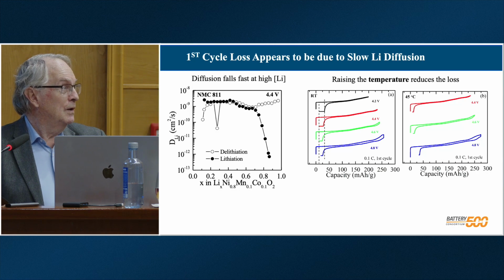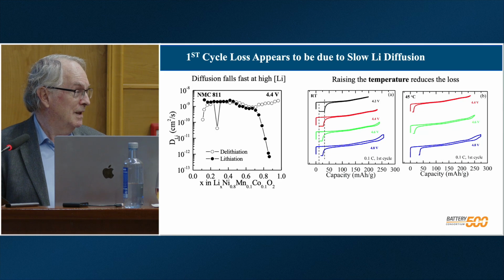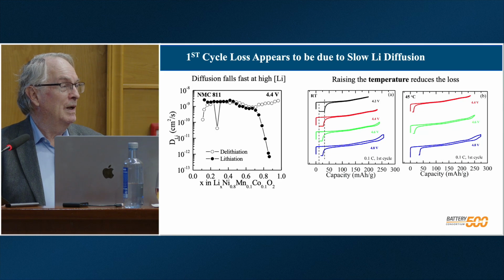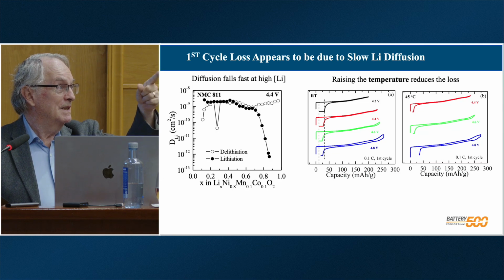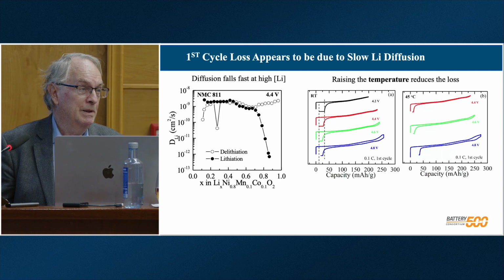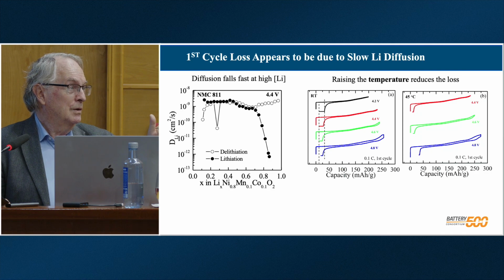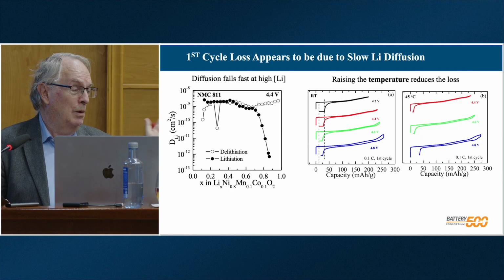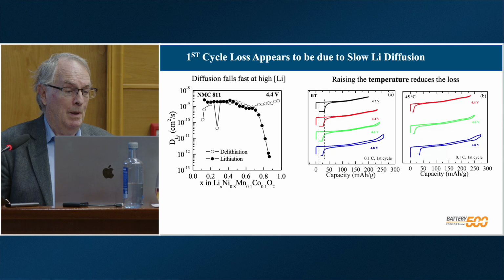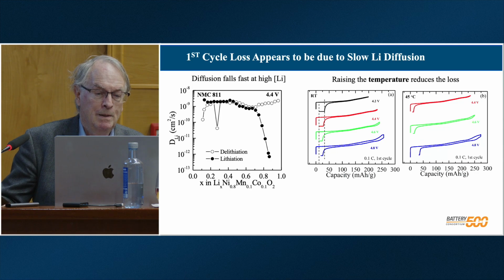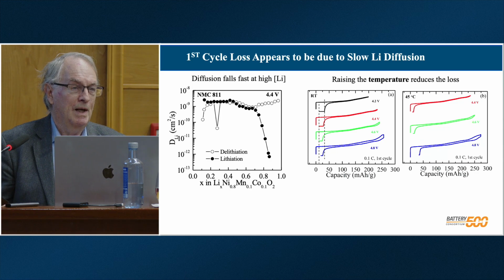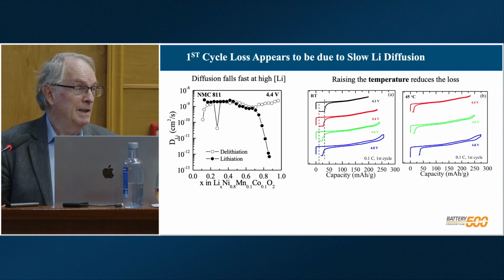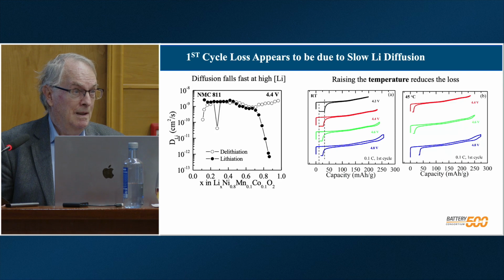Every aisle seat is full. If another person comes in, all of you have to move to fill those empty seats in the middle. And that's exactly what happens in these lithium materials. So to get the last 20–30% of the lithium in there, all the other ions have to move. And that's why it slows down dramatically. So what we decided, if that's really the case, if we raise the temperature, we shouldn't get such a loss, or if we doped it or substituted it in some manner.